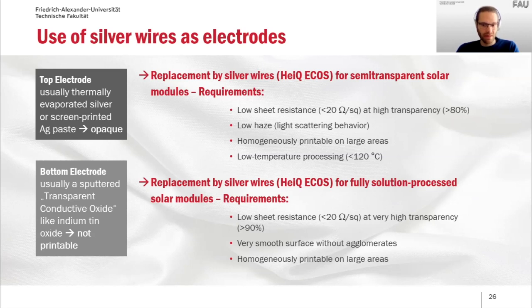So everything that absorbs or reflects at this position will decrease the current of the module. And another very important requirement for bottom electrodes is we need a very smooth surface without agglomerates because, as I said, the whole solar cell stack is less than 1 micrometer thick. And if the agglomerates of silver nanowires, for example, are larger than that, this would shunt or even short the device completely. And again, we need homogeneous prints.